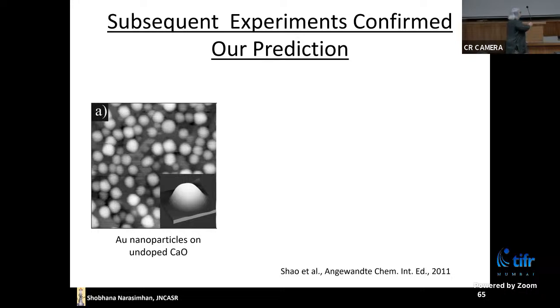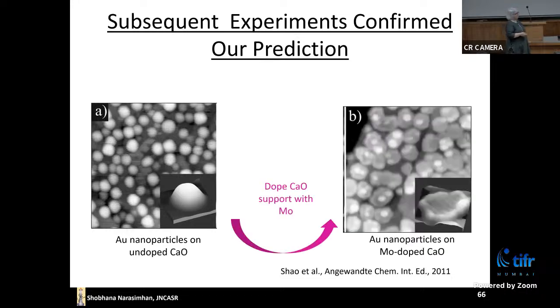So this is the STM image of it on the undoped oxide. So you see that the nanoparticles are clumped up. And then when they put it on the doped oxide, you see they're flat. They're just one atomic layer thin. They're like chapatis. Okay? So this is very exciting as a theorist, that you predict something and someone does the experiment and it works. Okay?